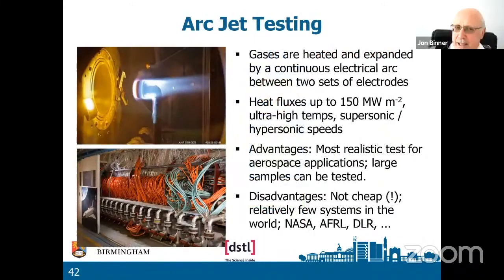A much better test and a much more expensive test is the ArcJet. So we developed our systems for rapid screening. Is material A better or worse than material B? When you really want the testing done and you want to get results for publishing, you really need ArcJet testing. But these tests will cost something like 25,000 euros per sample.